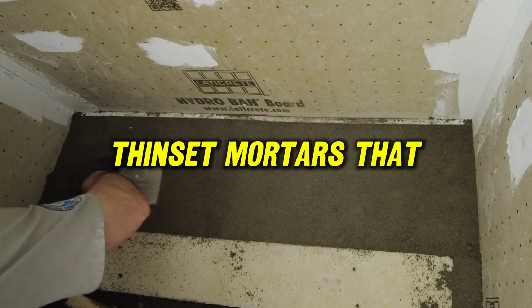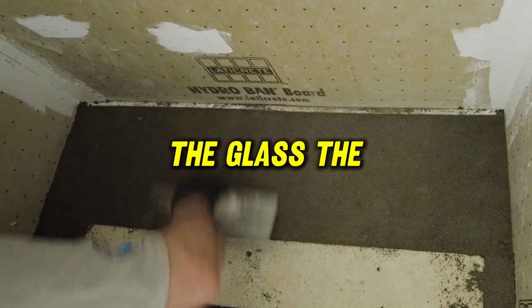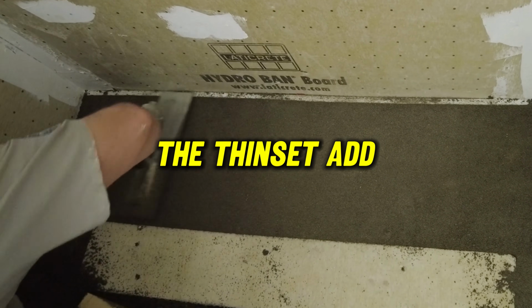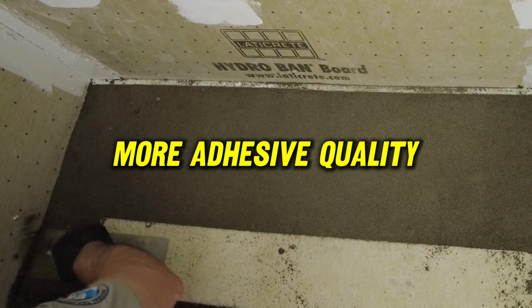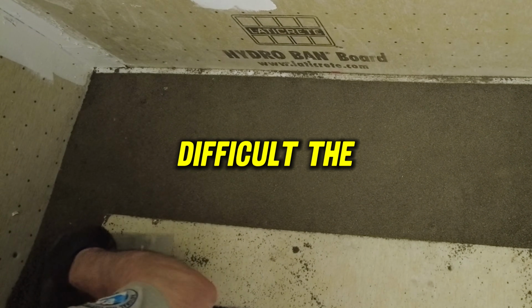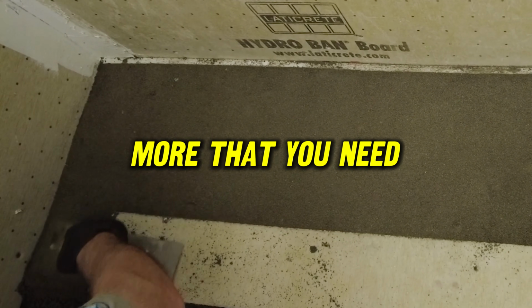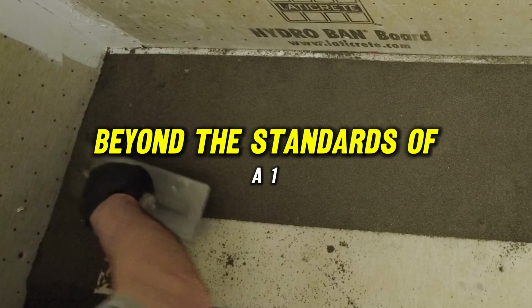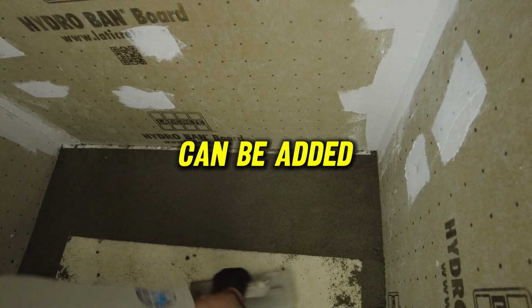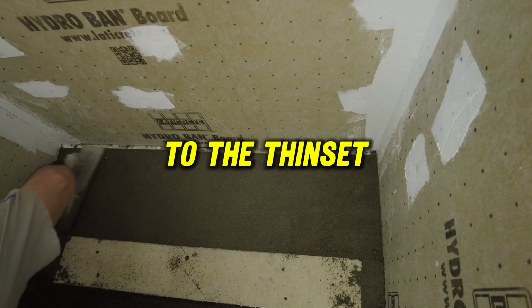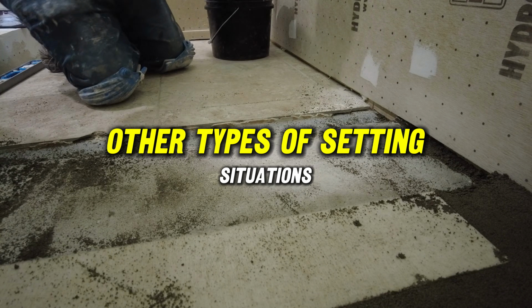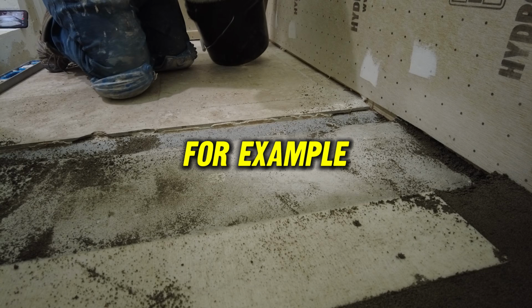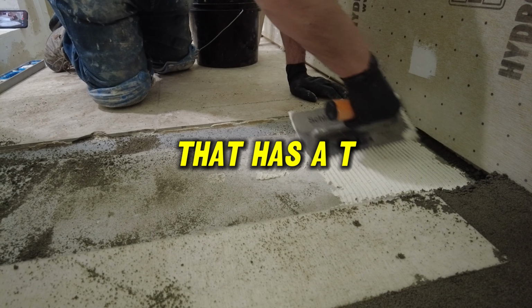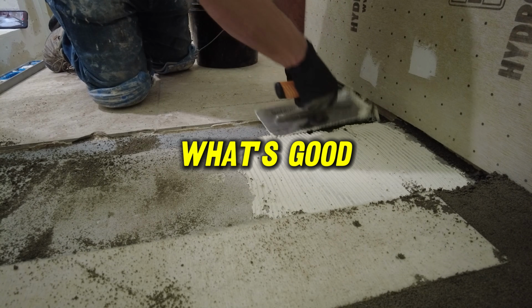So 0.15 has a better adhesive quality and will stick to usually glass. They also make Thinset mortars that are specifically made for glass. The polymers in the Thinset add flexibility and more adhesive quality to it. The more difficult the substrate is to adhere to, the better quality mortar you need. Beyond these standards of A118.4, 0.11, and 0.15, there are additional qualities that can be added to the Thinset to make it useful for other types of setting situations. For example, if you get a mortar that has a T at the end, so it's going to say it's got an